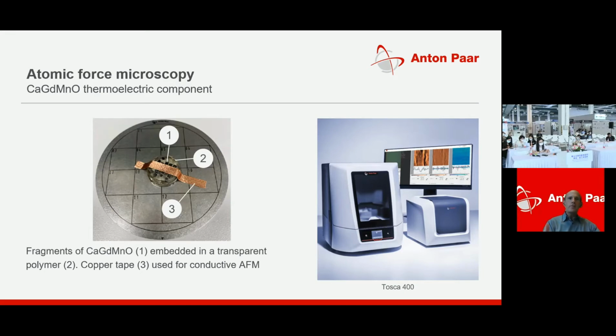For this purpose, we put sample fragments of calcium gadolinium manganese oxide into a polymer resin and polished this fragment of samples. The copper strip that you see in this picture was only used to perform some additional conductive mode measurements using the atomic force microscope. So it's not important for the magnetic mode of measurement.